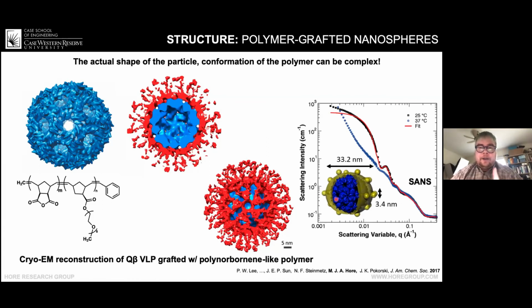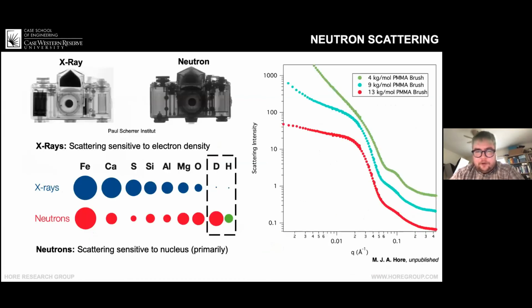But you hit on an excellent point, which is that sometimes these changes are subtle, but these subtle changes in slope out here, for example, let me blow it up so we can look at something bigger. If the slope out here on a double log plot went from -2 to -1.67, I mean, that's huge. That's the difference between a Gaussian chain and a swollen coil. So even though they seem subtle, they're a hallmark signature of these structural changes. Very distinct. Thank you, Mike.